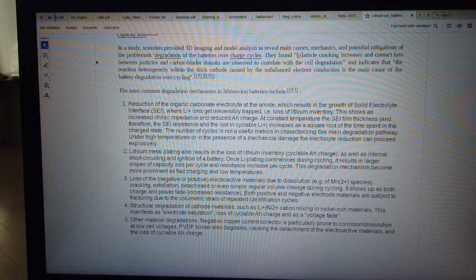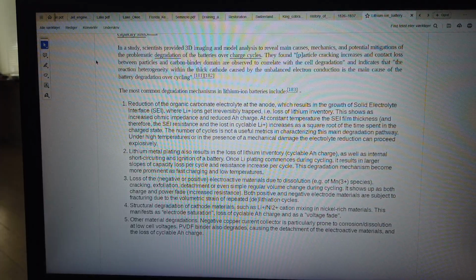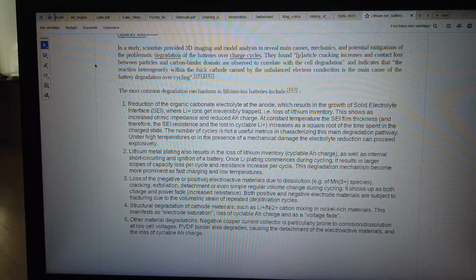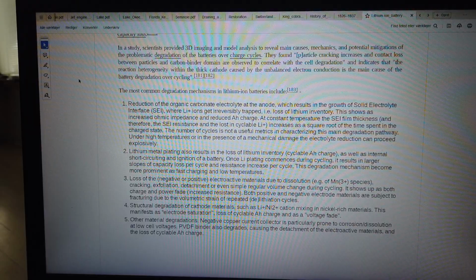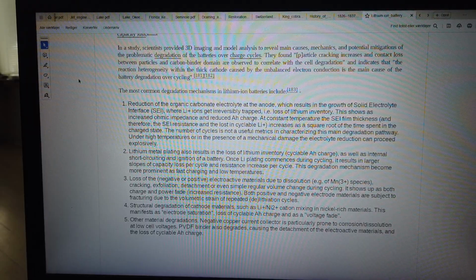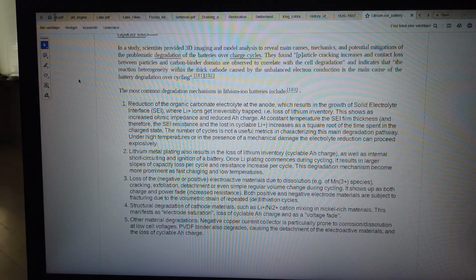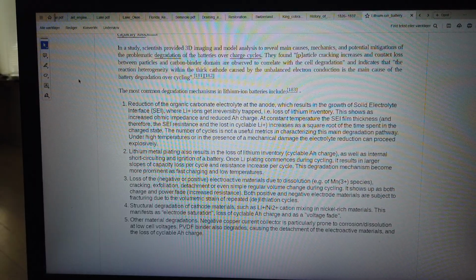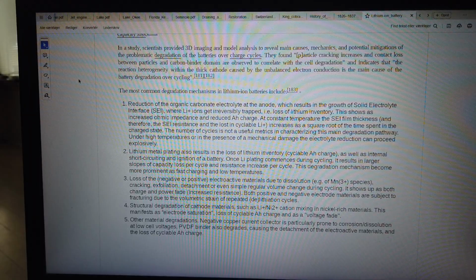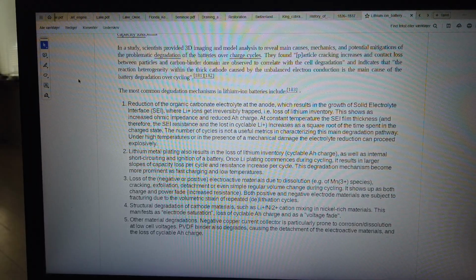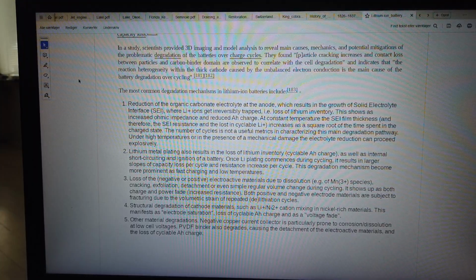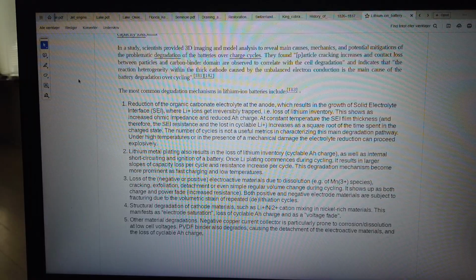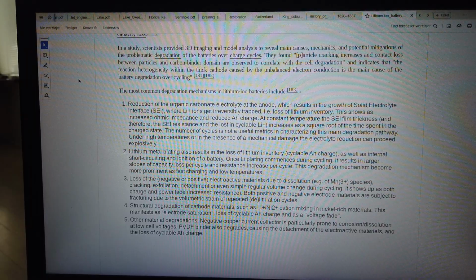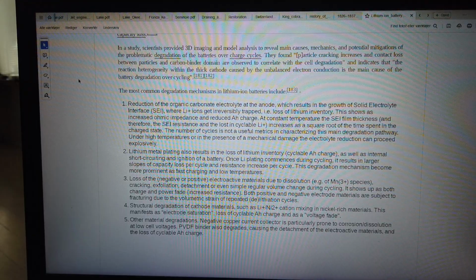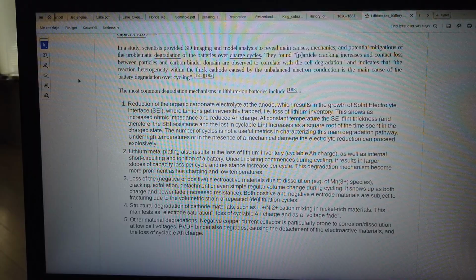The most common degradation mechanisms in lithium-ion batteries include reduction of the organic carbonate electrolyte at the anode, which results in the growth of solid electrolyte interface, SEI, where Li+ ions get irreversibly trapped, i.e. loss of lithium inventory. This shows up as increased ohmic impedance and reduced cyclable charge. At constant temperature the SEI film thickness, and therefore the SEI resistance and the loss in cyclable Li+, increases as a square root of the time spent in the charged state. The number of cycles is not a useful metric in characterizing this main degradation pathway.